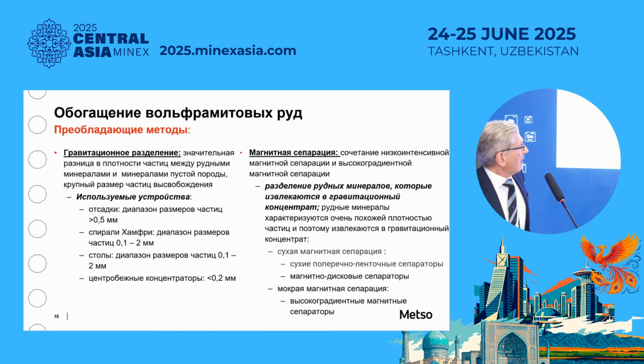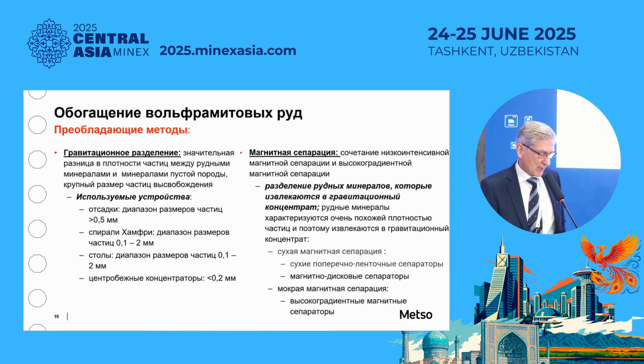Well, beneficiation of wolframite ores, we have gravity separation. Yeah, that's what we said, in the coarse particle size range and in the finer particle size range. And as wolframite is a paramagnetic mineral, we then use high gradient or high intensity magnetic separation.